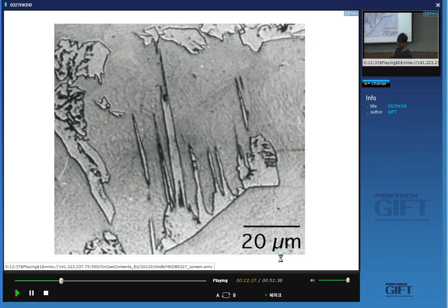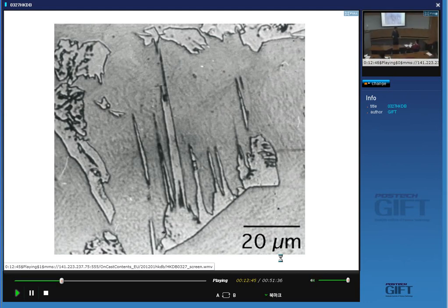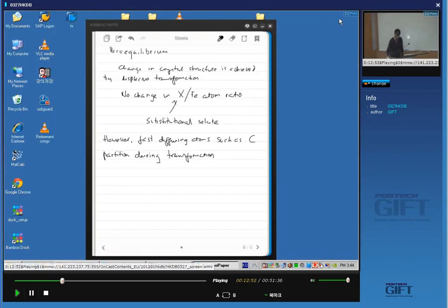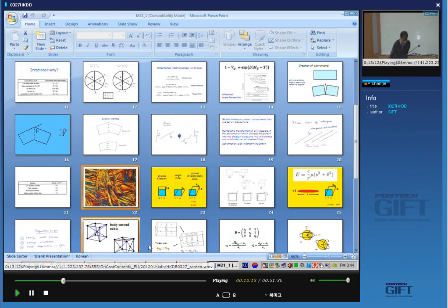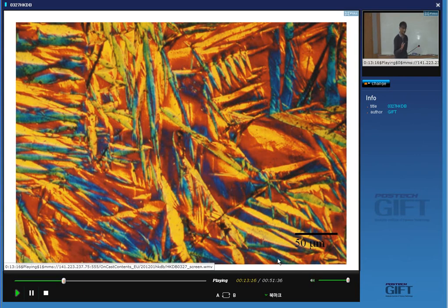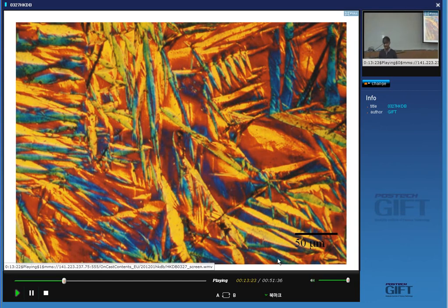So let me give you a clue — we had the interference micrograph showing the beautiful colors of martensite plates. We polish a sample completely flat, allow it to transform into martensite, then the surface is tilted everywhere you have martensite. Interference microscopy relies on height differences. This is an optical interference micrograph — so you could do an experiment like that.